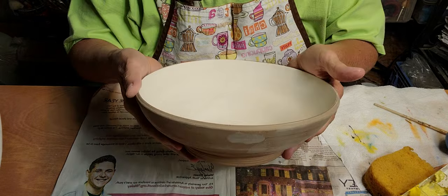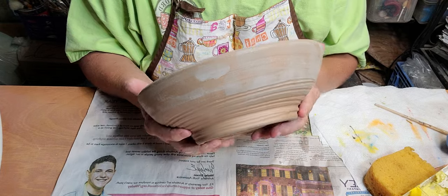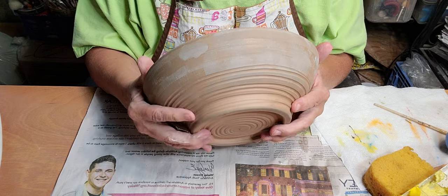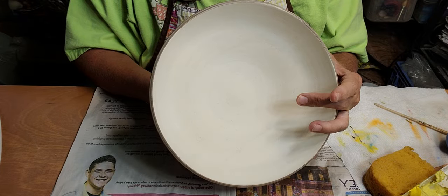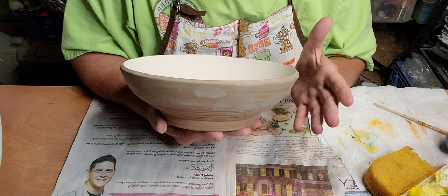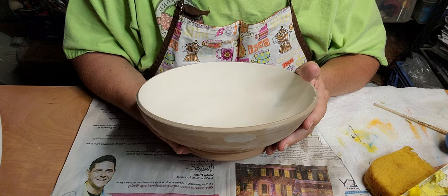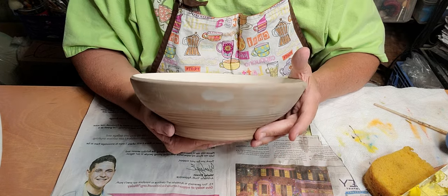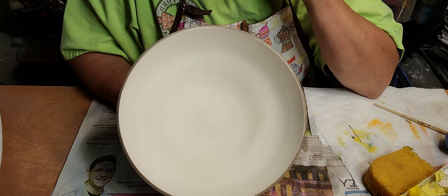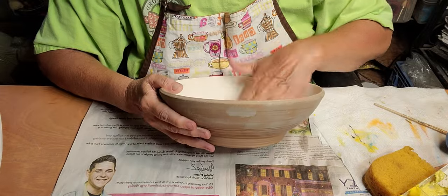This is Standard 266 clay. It's a dark clay - when it fires you can see a white residue there that will burn out and it'll be a very dark brown clay. On the inside I put a white slip. Standard 266 is cone 5-6. You don't really want to go to cone 6 on the dark clay - especially this 266, it tends to bloat. I fire at cone 5 with about a 10-minute hold, which usually takes me up to about 5 and a half. I put slip on the inside which I made from B-Mix 5 - my mistake was using B-Mix 5 with grog - so it has a slight texture to it from the grog and it's not as smooth as what I'm used to.